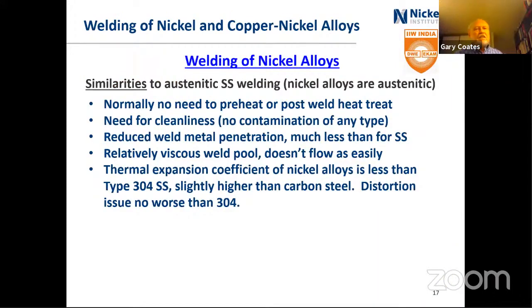So there are a lot of similarities between welding of the austenitic stainless steels and the nickel alloys. And in a way, the nickel alloys are all austenitic alloys, just like the 300 series stainless steel. So there's no need to preheat or post-weld heat treatment. Need for cleanliness, even greater for the nickel alloys. Reduced weld metal penetration, I'll come to that shortly. The weld pool is viscous. It doesn't move, it doesn't flow easily, and that is just a natural characteristic of the material that the welder has to live with. And we'll get into that shortly too.